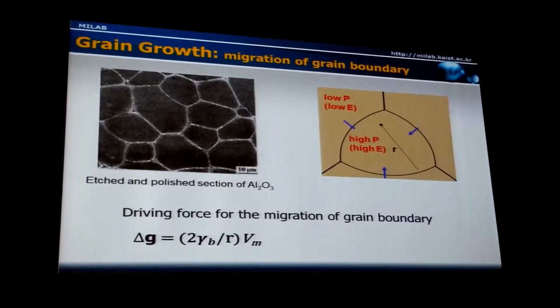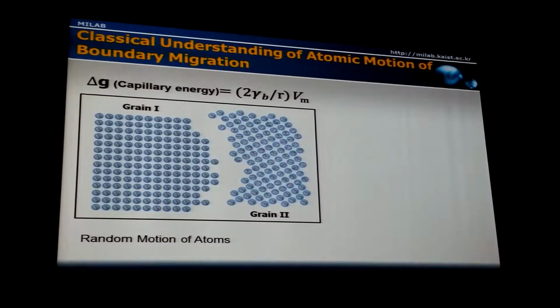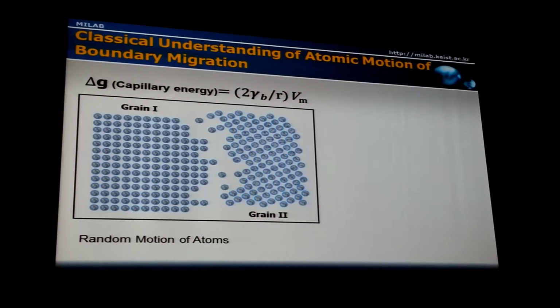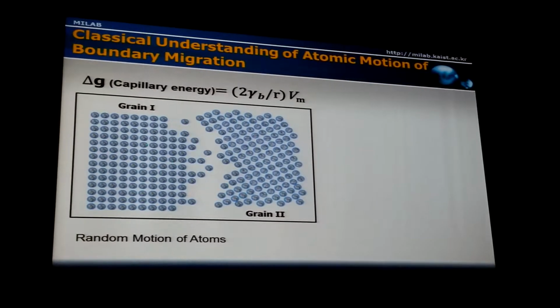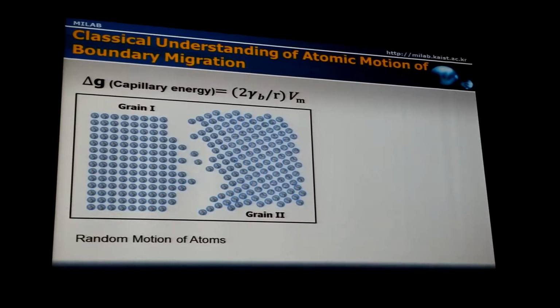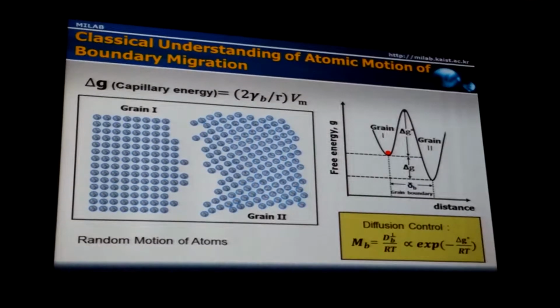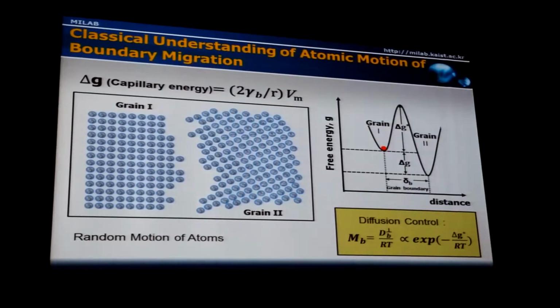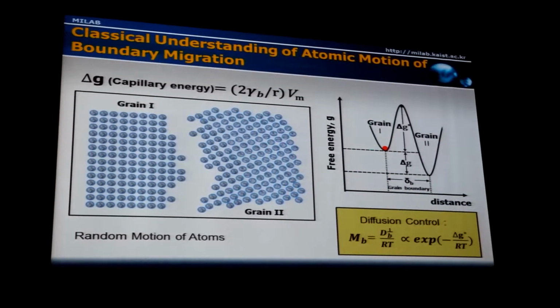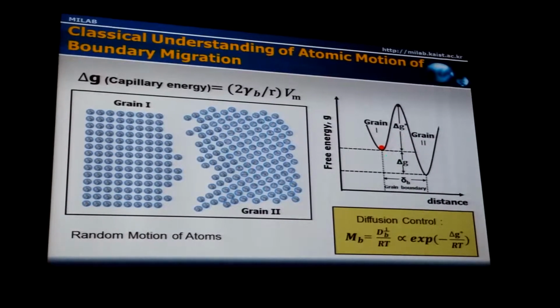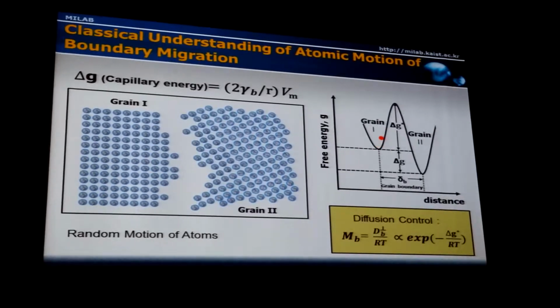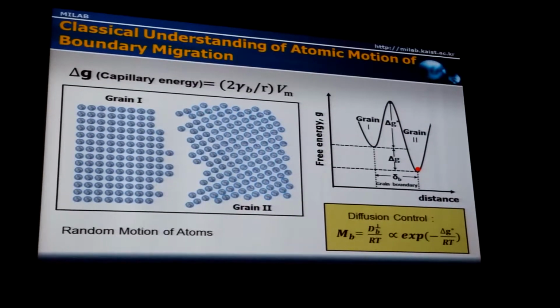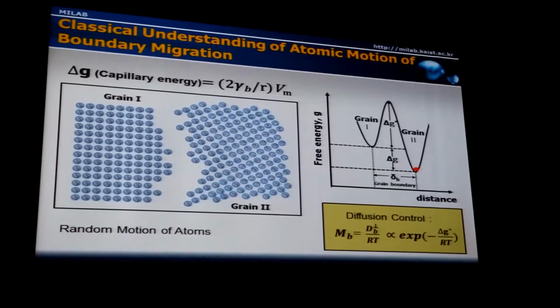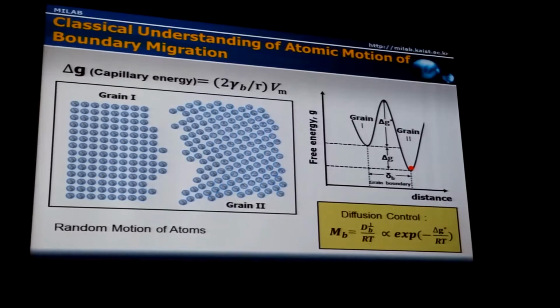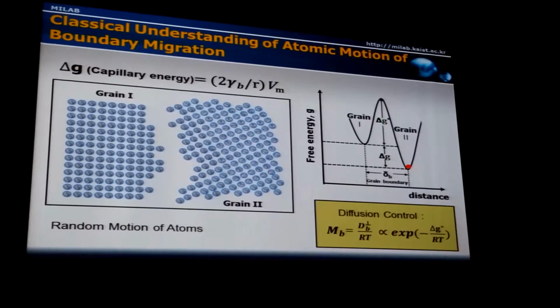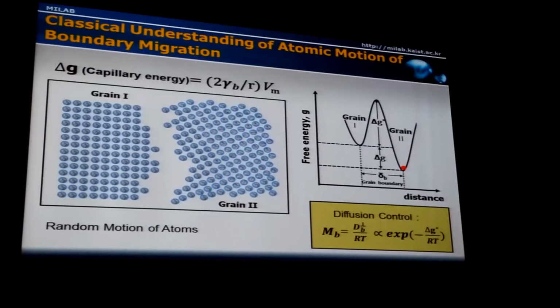Then, how about the atoms in motion under this capillary pressure? Atoms will jump across the boundary from the grain with high chemical potential to low chemical potential. This process can be expressed by a simple free energy distance diagram from one grain to the other grain. There is a capillary energy difference, and because of it, the atoms will move from one grain to the other. Of course, for the movement, there is an energy barrier because of the energy instability of the atom between the two grains, which is expressed by delta G star here. We call it the activation energy for diffusion.